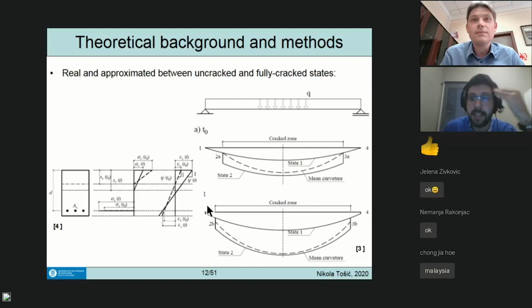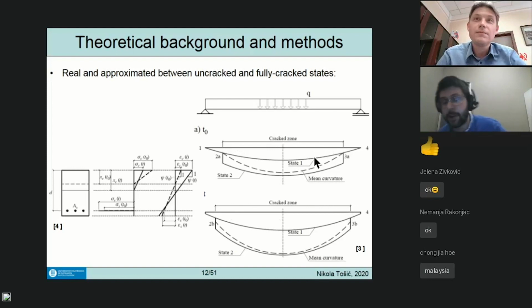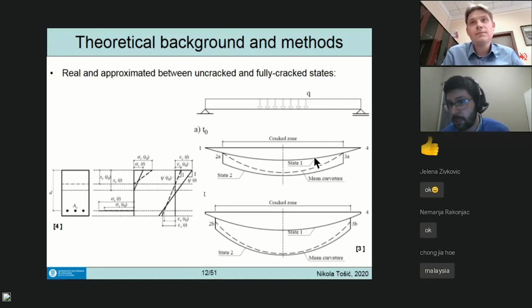Also, what happens - maybe I should have pointed this out - is that the cracked zone is going to extend as well. Here it's wider than it was before. So new cracks are going to open over time. Why? Because basically shrinkage eats up your tensile strength in parts of the concrete and opens new curvatures. You'll see in modeling how this is achieved. There is, over time, a reduction of your cracking moment.